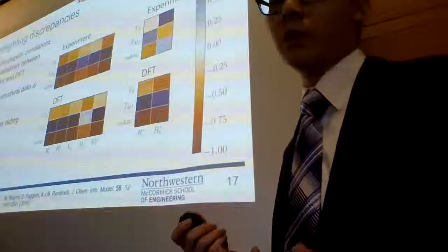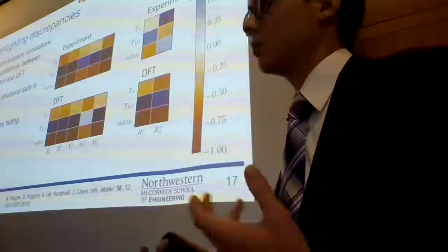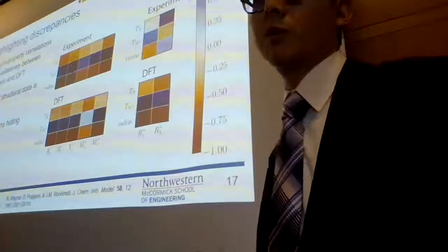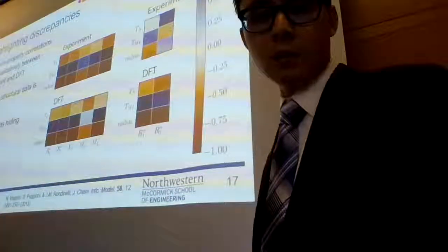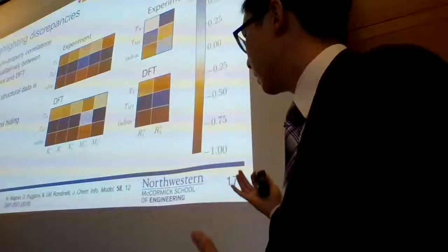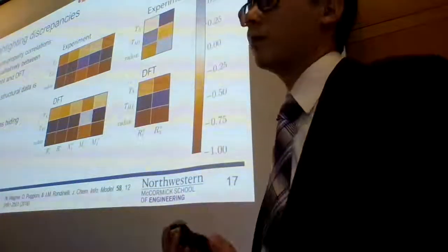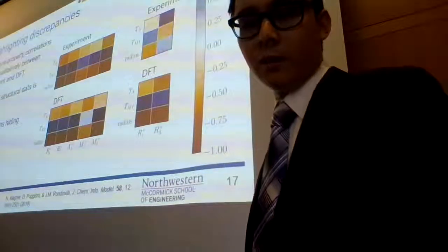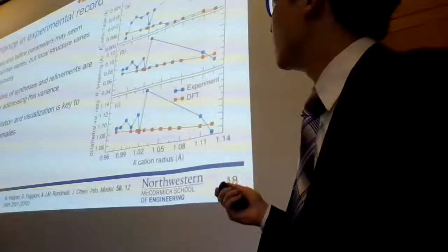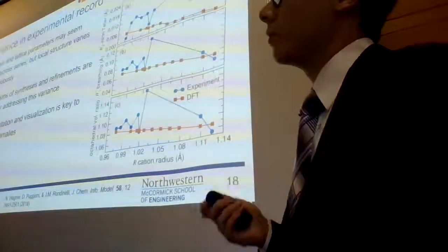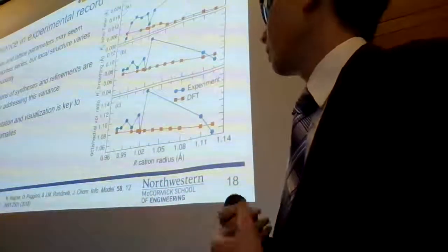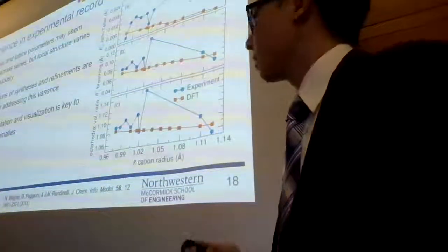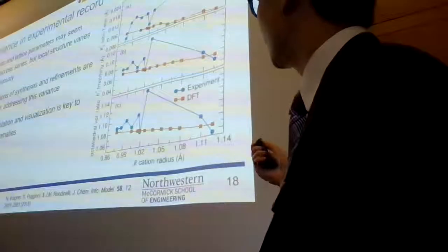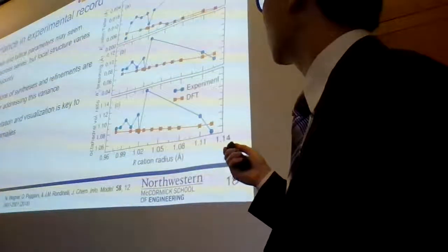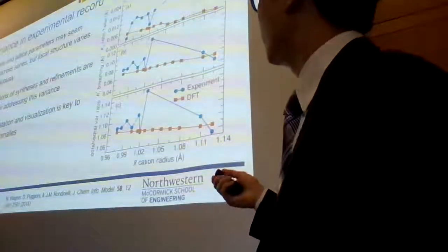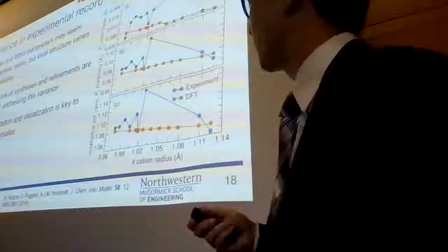So why would just looking at the structural information lead you to conclusions that are opposite between experimental reports and what's computed computationally? One important thing to keep in mind when doing any sort of data science study is, where did the data come from? What's the context behind how it was created? One thing to point out is that in density functional theory, the structures are all treated on essentially the same basis. They relax under the same conditions with similar pseudopotentials. As a result, you notice this pretty sensible trend that as the A-cation radius gets larger, as the steric packing leads it to be more cubic, all the distortion amplitudes go down, as you would expect.